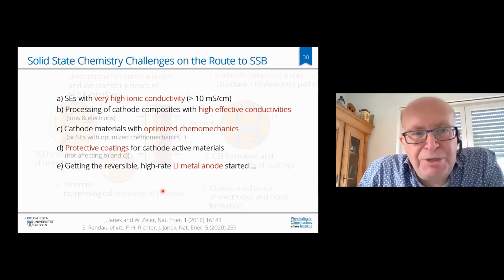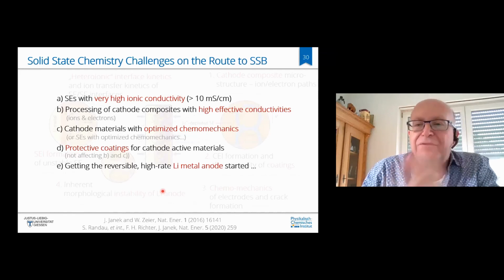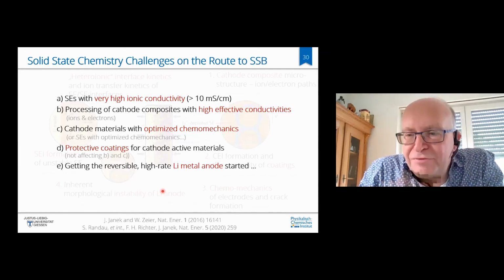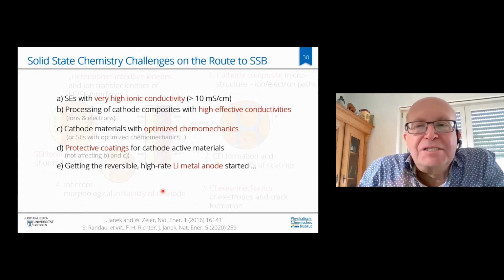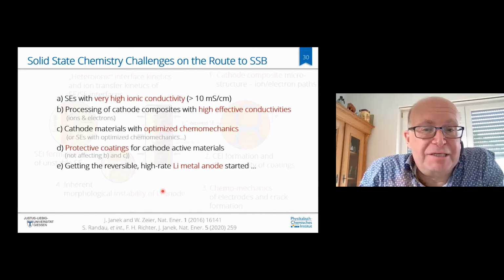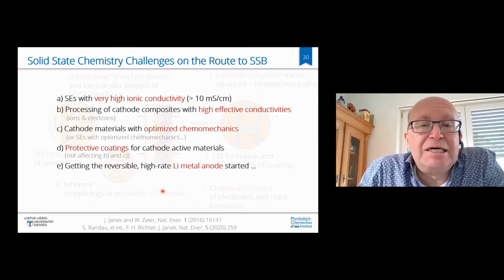I think we need processing of cathode composites with high effective conductivities. It's not enough just to take the electrode and say, okay, this has a high conductivity. The effective conductivity has to be high because tortuosity effects may be critical. Chemomechanics has to be overcome, the issues with that. We need protective coatings in order really to keep the sulfide electrolytes, I would say, alive for long enough cycles, high enough cycles. And I think the high rate lithium metal anode is still a challenge, but I will of course be happy to learn whether QuantumScape or Samsung at the end find their ways to anode-free cells.